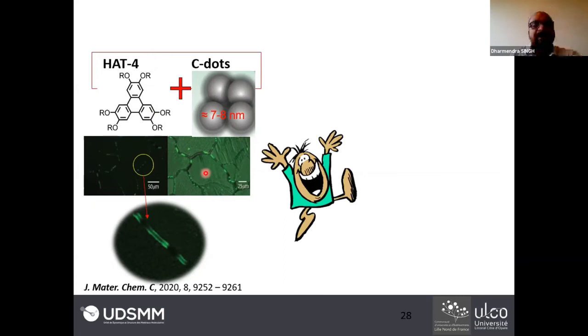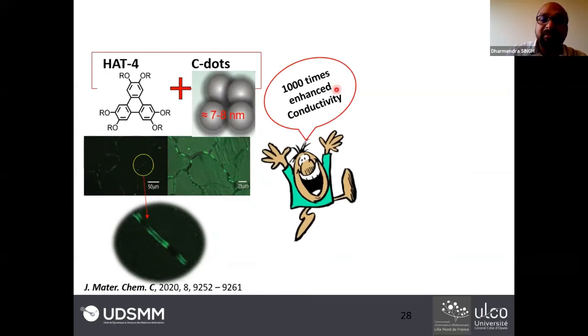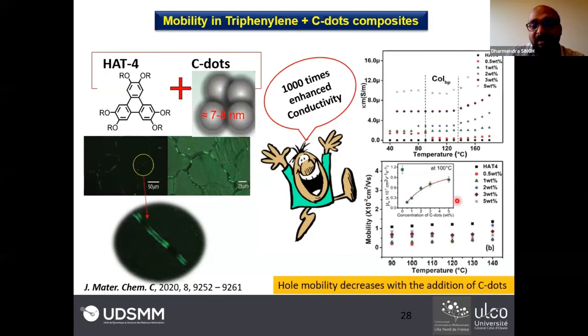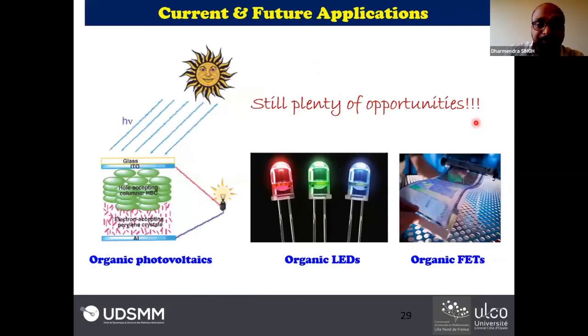And that's why they enhance the conductivity a lot, because all the organic semiconducting molecules, especially these discotic liquid crystals, show poor conductivity. This is the problem with these materials, and it is a challenge in front of all experimentalists to enhance the conductivity. By adding this, we have enhanced the conductivity by 1000 times. The mobility of the charge carrier is reduced, but only by 1%. So the mobility has not been affected significantly, but we have successfully enhanced the conductivity 1000 times, and that is really very interesting for organic electronic applications.